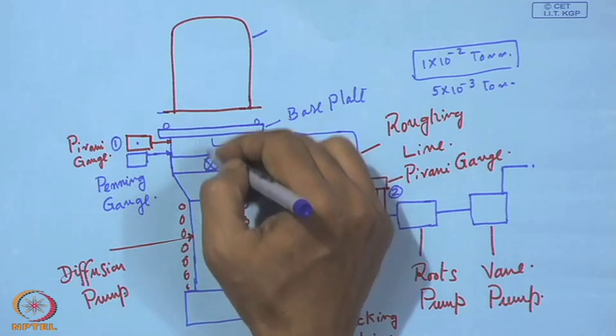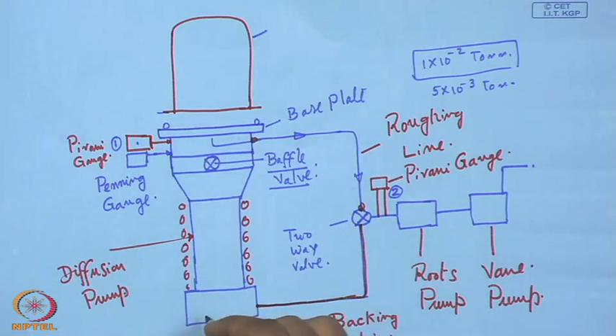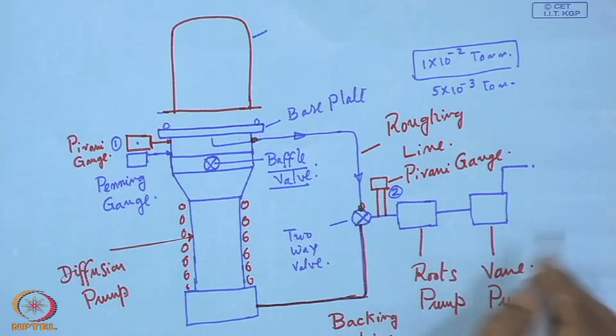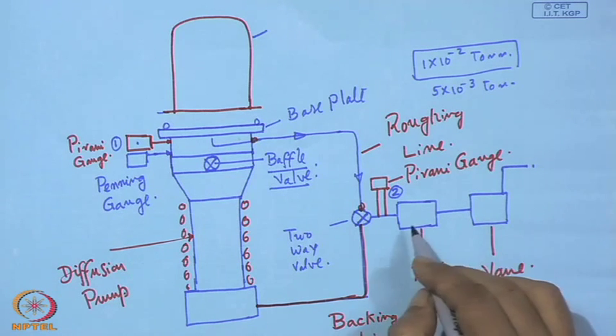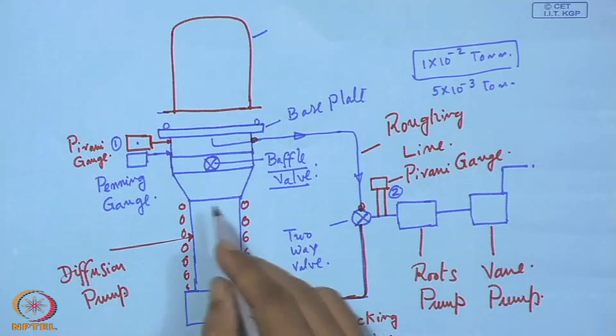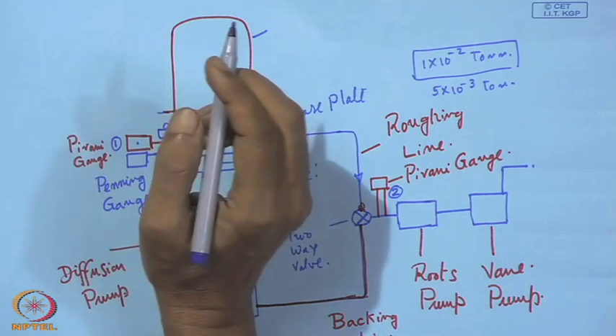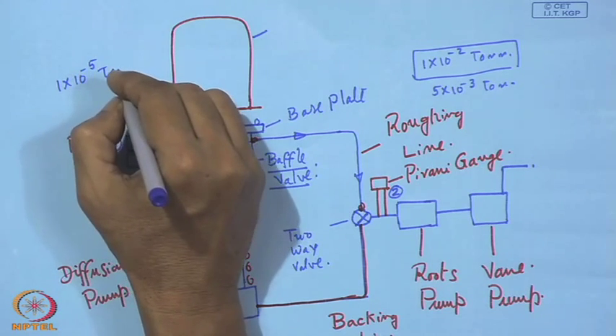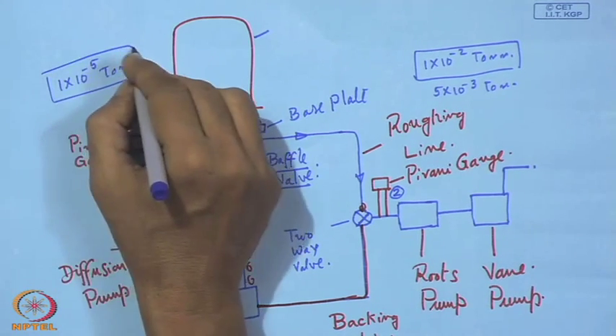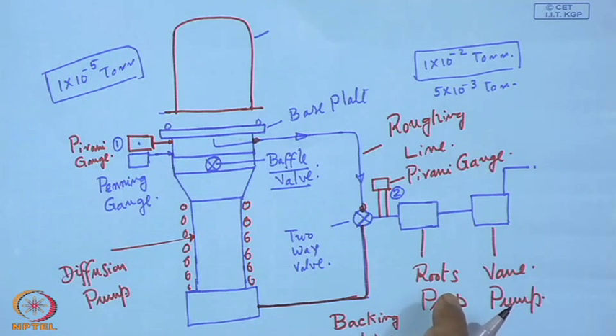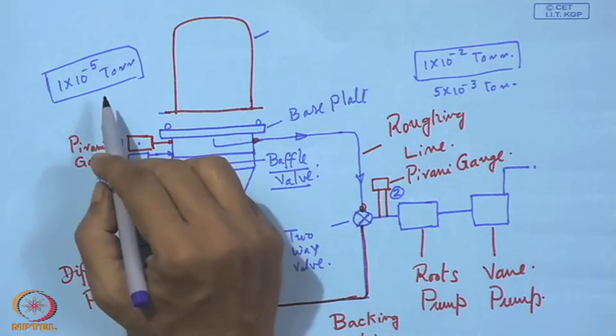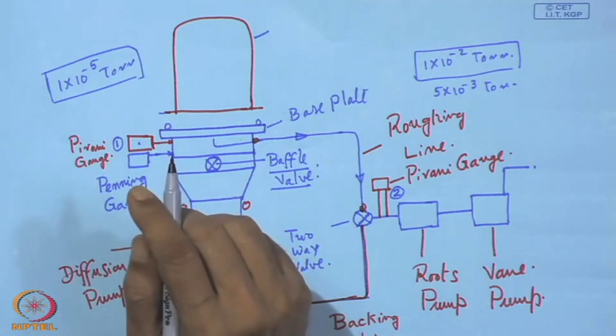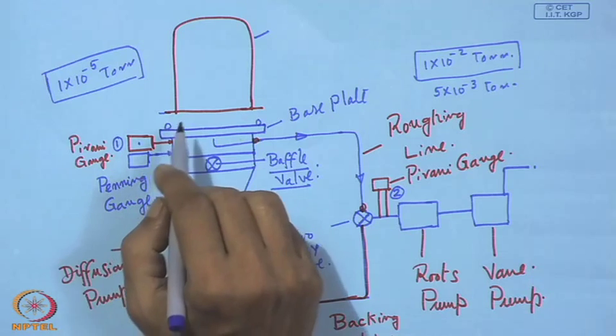The residual air will be sucked through this diffusion pump and roots pump - these are the backing support. That will give the required support to this diffusion pump, and with that a pressure better than 10 to the power minus 5 torr should be obtained. With a good system with minimum leak, it is not difficult to attain a pressure better than 1 into 10 to the power minus 5. This is actually a high vacuum system, what is necessary for evaporation.